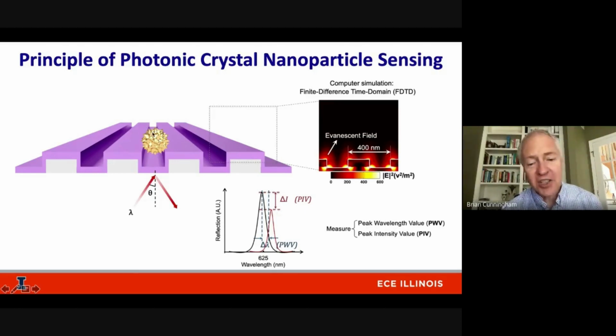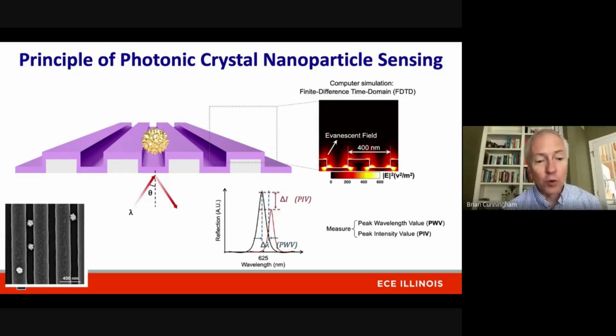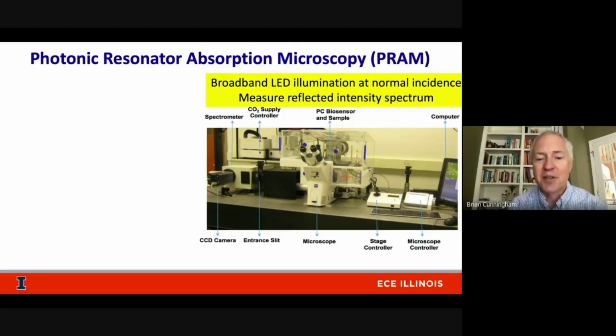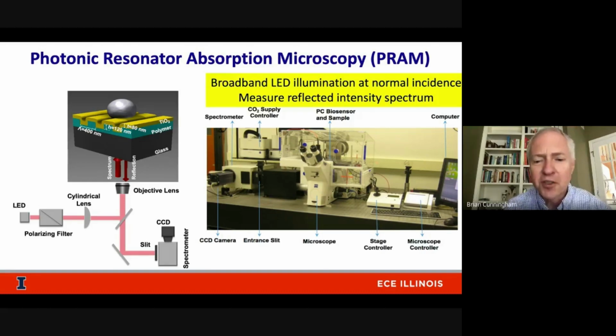But this reduction in the reflected intensity is very localized only to the place where the gold nano-urchin is. If we move away from the gold nano-urchin by several micrometers, this effect does not happen. So it's a localized resonance quenching effect. And that tells us perhaps there's a method we could use for microscopy. This is where we're leading into the photonic resonator absorption microscope, which is really just a modified bright field microscope with the schematic shown here, where we can take light from a low intensity LED, so no lasers, no blasting with huge amounts of energy needed here.